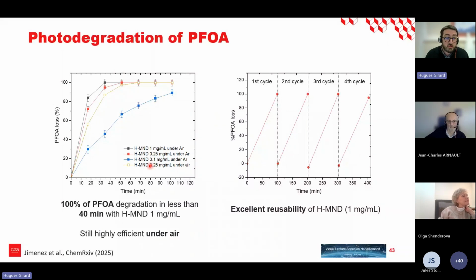And also, which is important, it is still highly efficient even in presence of air, because all the experiments were done under argon, but we tried without bubbling argon, and we observed that finally this is not an issue. It can also work in aerobic conditions. Then, of course, we tried the reusability of the system, which is also very good. So here it means that after degrading all the PFOA, we keep the same nanodiamond, we just remove the PFOA and the subproducts, and then we put back fresh PFOA, and you can see that you can repeat the experiments without any modification of the efficiency.